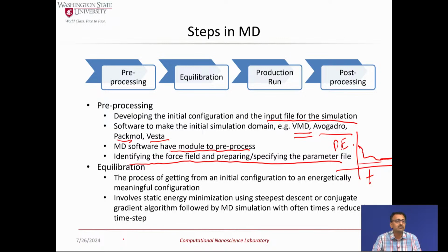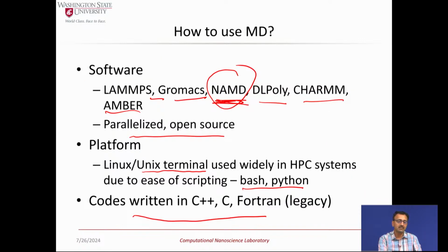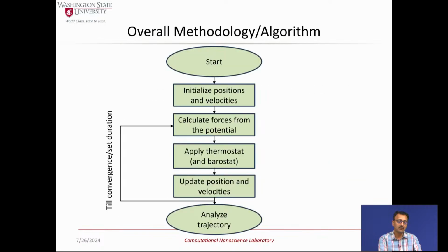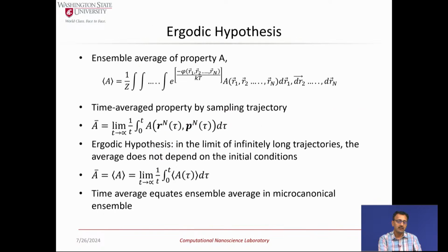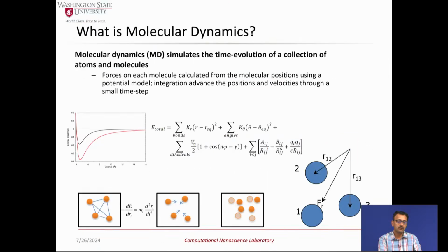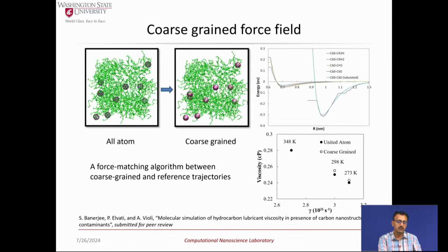Now, there are some tricks in the community, some standardized processes to do that. For example, you start with time steps that are smaller a lot of times. If you have tricky systems that you're not sure about their configuration, you start with small time steps, because of what that does in your Verlet algorithm. If I can perhaps go back here, I have the Verlet algorithm.